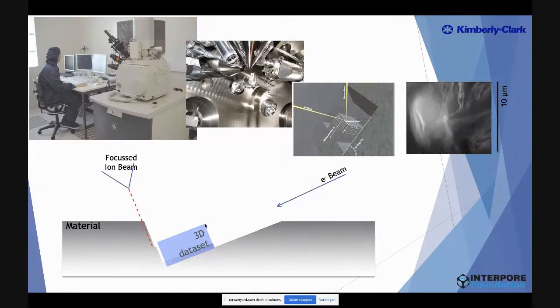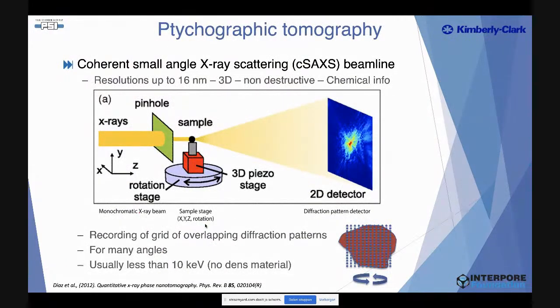If you want to go for non-destructive 3D imaging at high resolution and be able to also control, for instance, the environment around your sample, you can go for nano... well, you have different names for it. So it's ptychographic tomography or X-ray phase nanotomography. This is done at the synchrotron, and we did this at the cSAXS beamline, the coherent small angle X-ray scattering beamline at PSI. And there we could get resolutions up to 16 nanometer in 3D in a non-destructive way. And it also gave us chemical information. So for more details, I refer to the article of Anna Diaz.